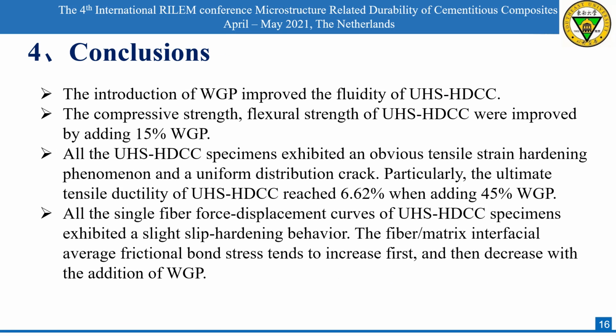The last part, conclusions. The introduction of WGP improves the fluidity of UHS-HDCC. The compressive strength and flexural strength of UHS-HDCC were improved by adding 15% WGP. All the UHS-HDCC specimens exhibited an obvious tensile strain hardening phenomenon and a uniform distribution of cracks. Particularly, the ultimate tensile ductility of UHS-HDCC reached 6.62% when adding 45% WGP.